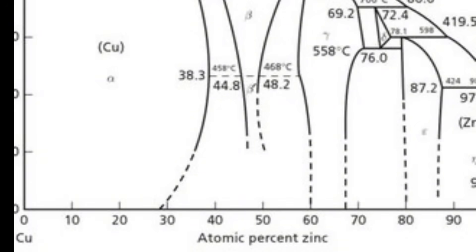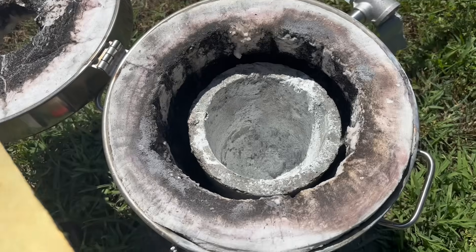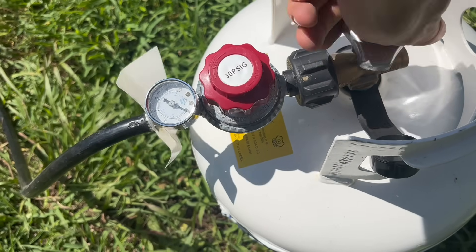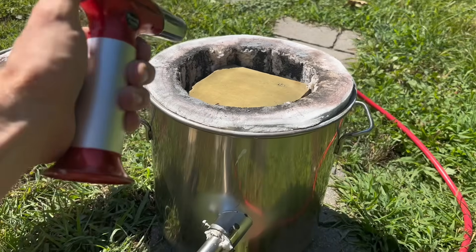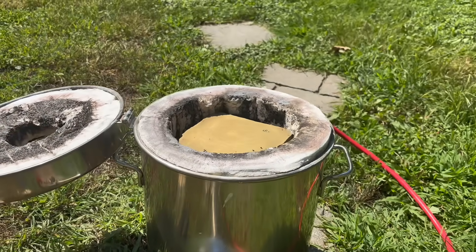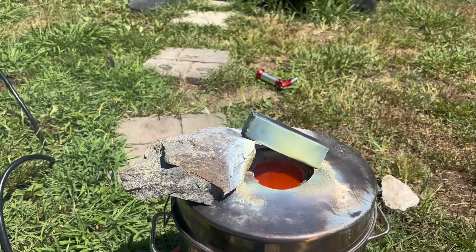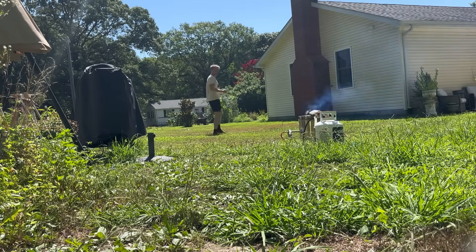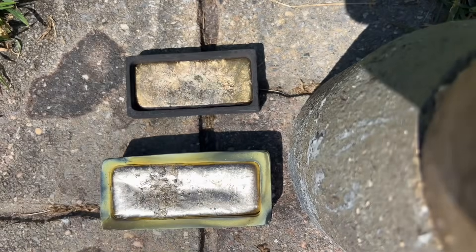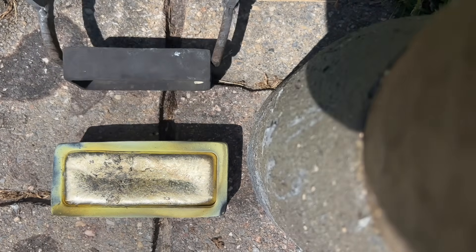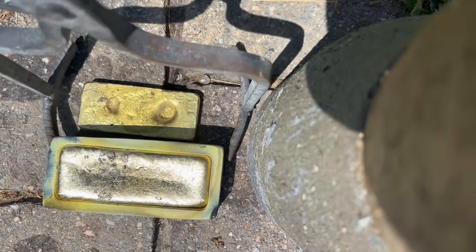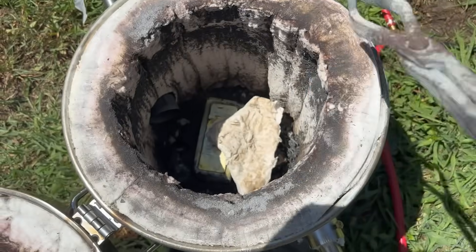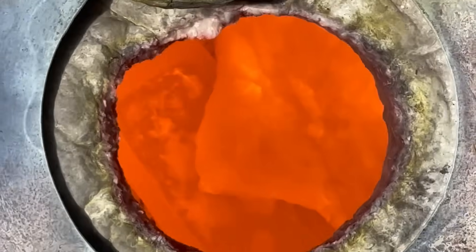Let's begin with 30% zinc 70% copper. Extremely conveniently I happen to have a big block of this exact composition so I threw it in the furnace lit it up and got to melting. One important thing to note about melting brass is that the boiling point of zinc is right around the melting point of brass. So there's definitely a correct way to melt brass without burning all your zinc. I'm a proponent of the incorrect way which is stand back and don't breathe in the smoke. After pouring our ingot we're able to take it put it back in the furnace remelt it and then allow it to cool extremely slowly relatively speaking over a period of about eight hours.